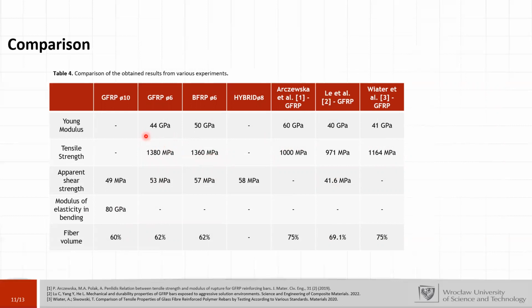In case of the Young modulus, we have 44 gigapascals for the GFRP and 50 for the BFRP. The Young modulus in the literature I've noticed is greater, but we need to be aware that the fiber volume is the crucial factor that decides the stiffness of the structure or material. In our case it's only 62%, and in the case of this data it's 75%. So that's why the Young modulus is greater.